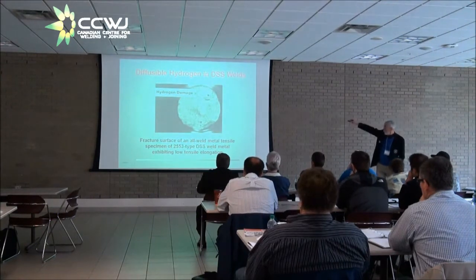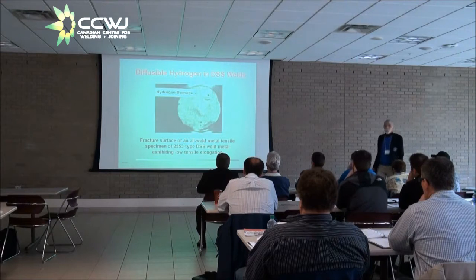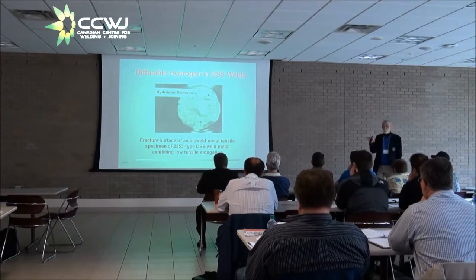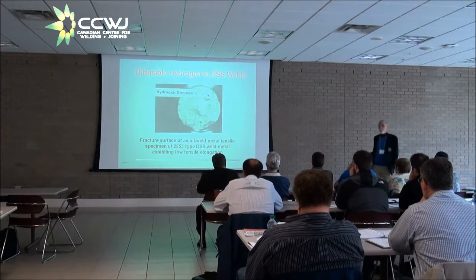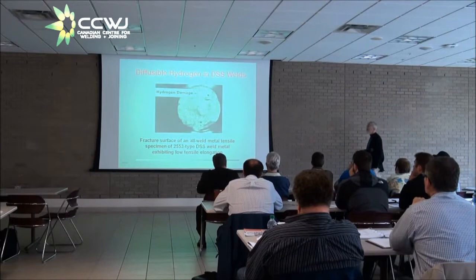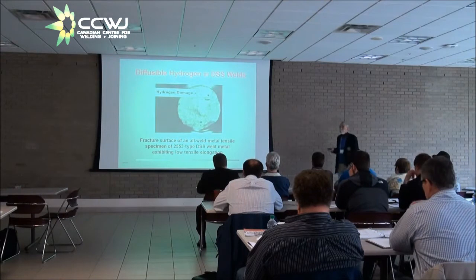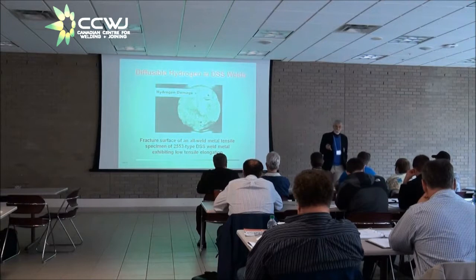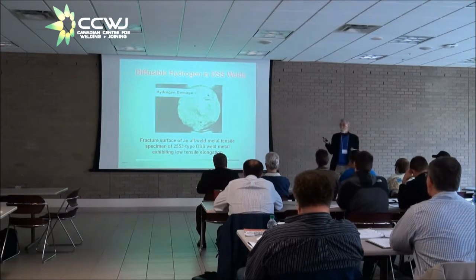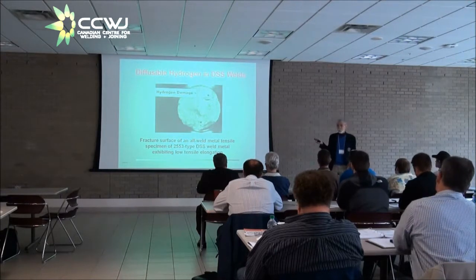Right here you have a very large fisheye. You guys work with low alloy steels, you know what I mean by fisheyes. They're crystalline fractures caused by diffusible hydrogen. The tensile elongation of that stuff is only about 10 or 12%. Whereas duplex stainless steel should be treated, when you're welding it, as if it were something requiring low hydrogen practice.